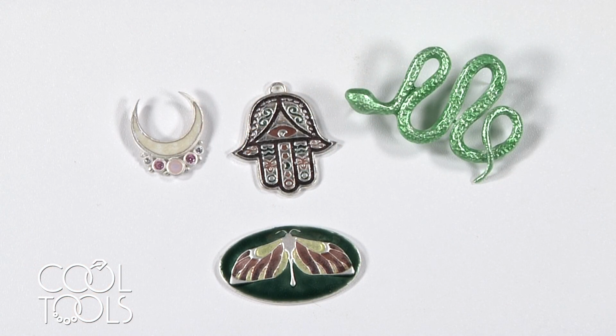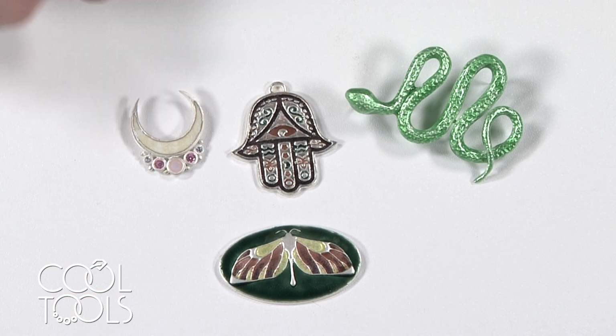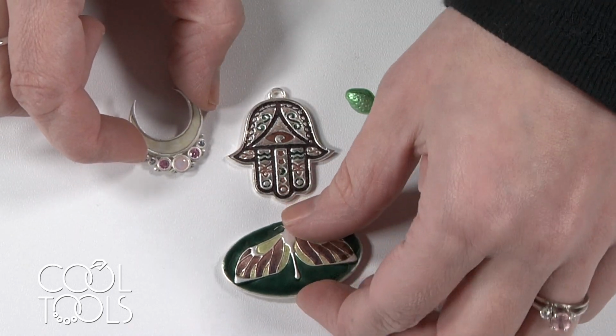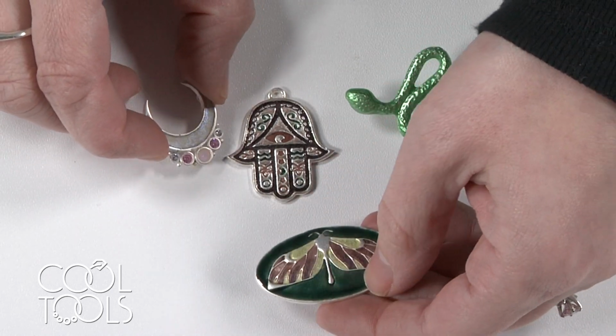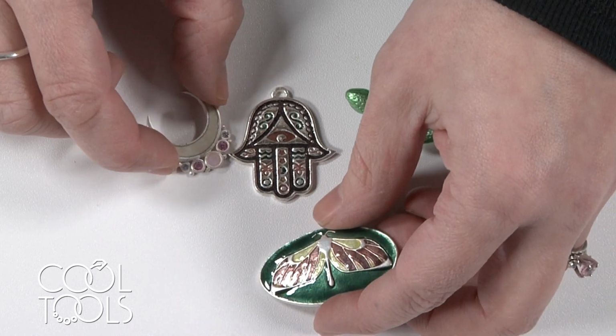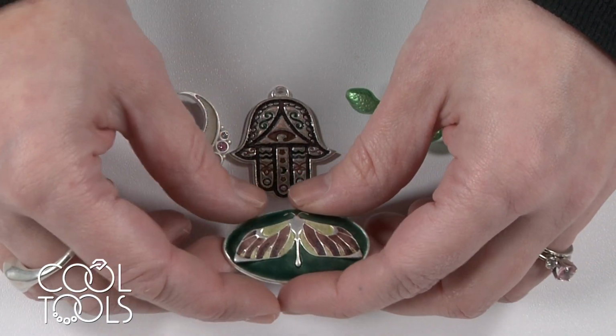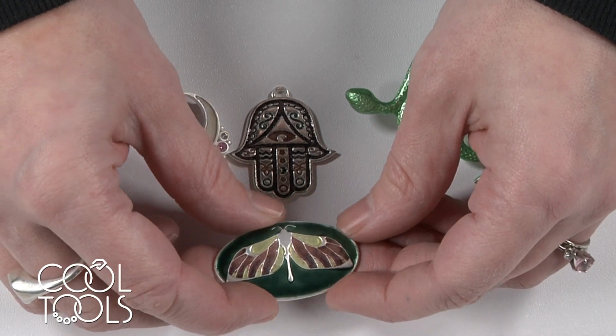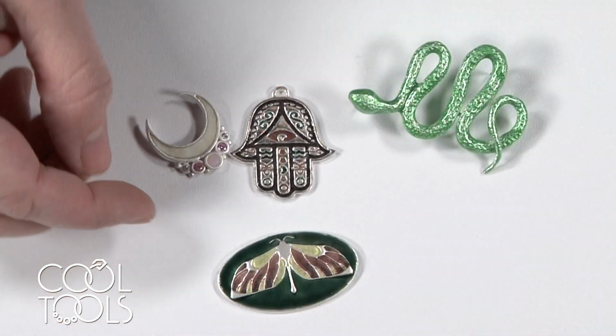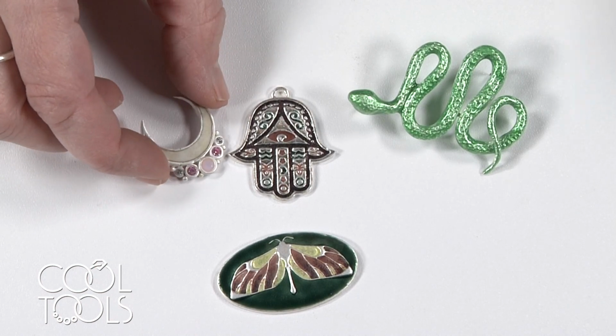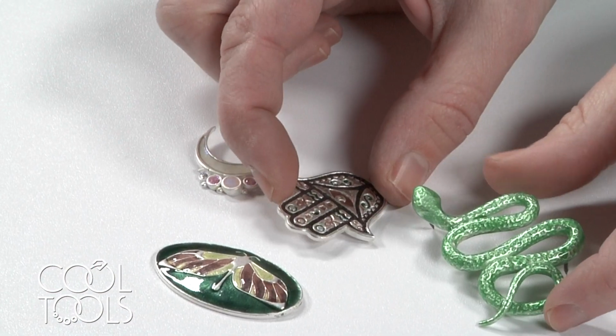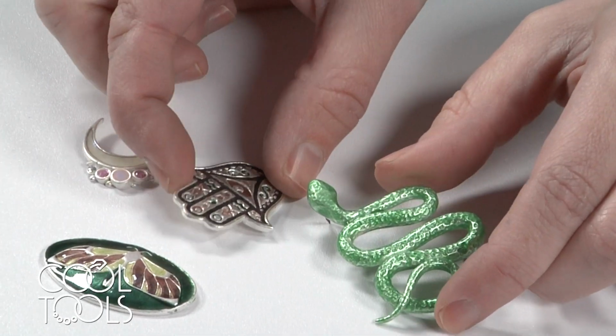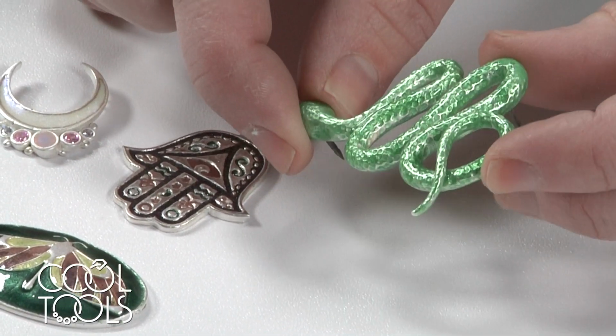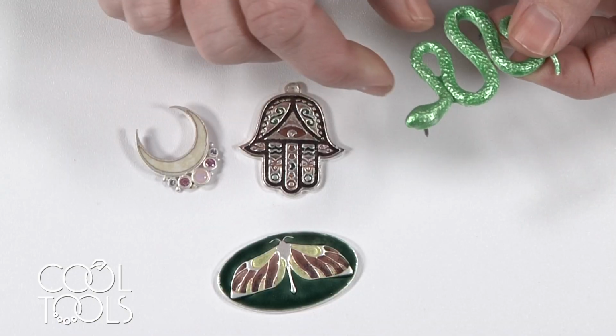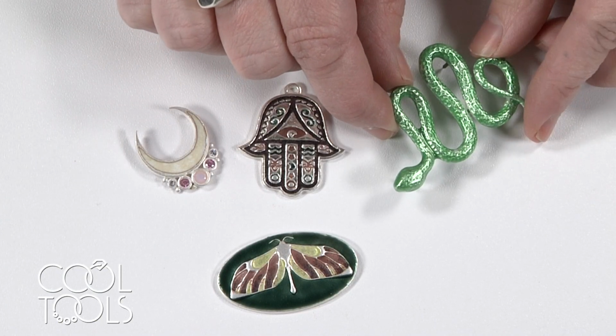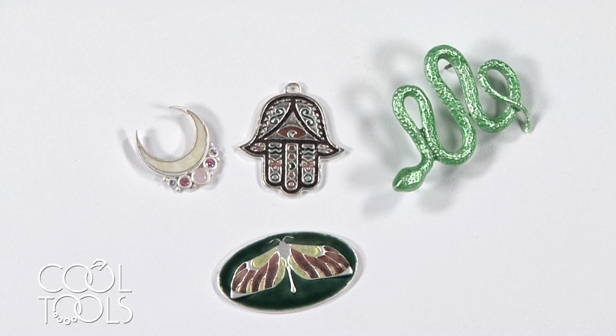In all the testing that I did, I was really happy with the way that this clay enameled. These 2 pieces were sintered with a torch prior to the enamel being applied. And again, they didn't really exhibit any soak or drawing away of moisture like you can sometimes have when you're enameling on precious metal clay. And that made it really easy to blend out colors, and the enamel lays on beautifully. These pieces were fired in a kiln, and I wanted to test out a Champlevé style enameling and then enameling on a three-dimensional surface. And again, it just enameled beautifully. I was really happy with the results of those tests as well.